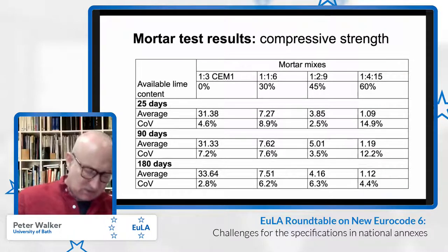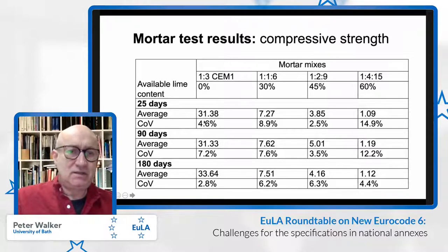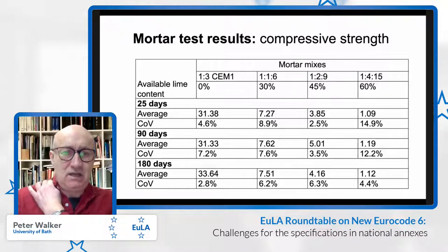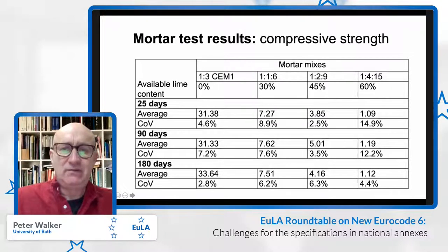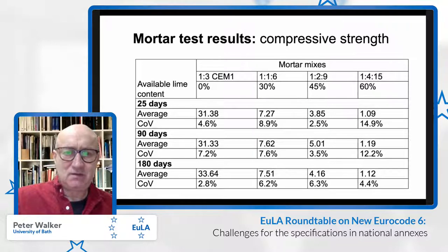In terms of the mortar test results, here are the average compressive strengths from the mortar tests. I haven't presented all of the data, for brevity, in terms of the flexural properties. This is the compressive strength of the four mixes, as mentioned earlier, over three different ages. The standard age for testing cementitious products is recognized as 4 weeks or 28 days. To clarify, the reason why we tested them at 25 days was to actually apply the creep load at that 28 day limit. So we tested the material 3 days earlier than the standard 28 days.